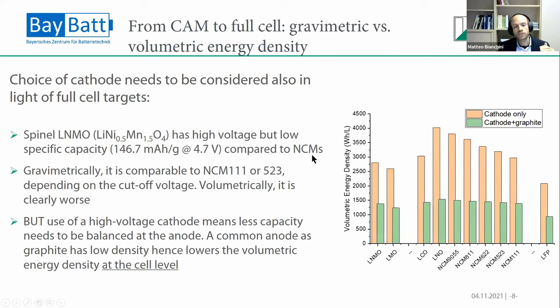And so if you look just at the gravimetric energy density of this LNMO at the material level, you will see that it's at most comparable with a past generation NCM material, the 111 or eventually the 523, depending on the cutoff that you use. But volumetrically, it is worse. And this is what you see in this plot here. So the LNMO is here on the left, and the NCM materials are here with higher volumetric energy densities.